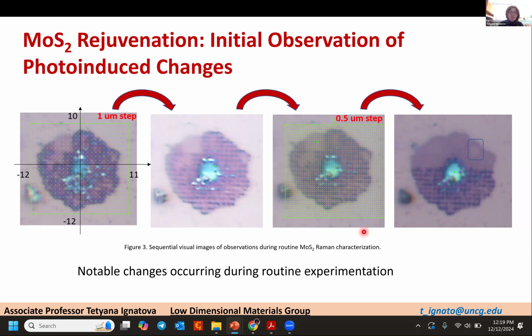That is optical characterization, nothing special. We also see in correlated Raman changes, we definitely see that at a certain point the sample became more clean, then the sample did not change much, but after applying more and more power, samples start to disappear. So we definitely saw some cleaning, then some changes, and the sample became better and better, and then samples start to disappear. It was photo etching.